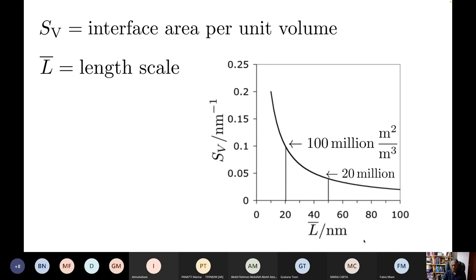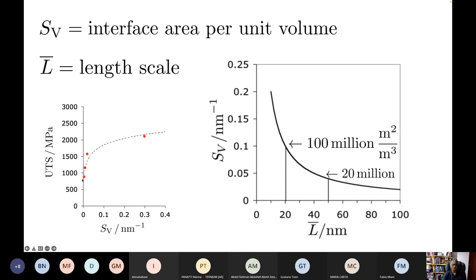The meaning of a nanostructure is that you have an exceptional amount of interfacial area per unit volume. I would say that nanostructure corresponds to the region of the curve where the amount of interface per unit volume rises sharply as the length scale decreases. Here we have 100 million square meters of interface per cubic meter. You change the length scale to 50 nanometers and you get a sharp reduction in the amount of surface and a corresponding sharp reduction in strength as you go to larger length scales. So if you can get a structure in which the interfaces are separated by something of the order of 20 nanometers, that genuinely is a nanostructure which will have exceptional properties.